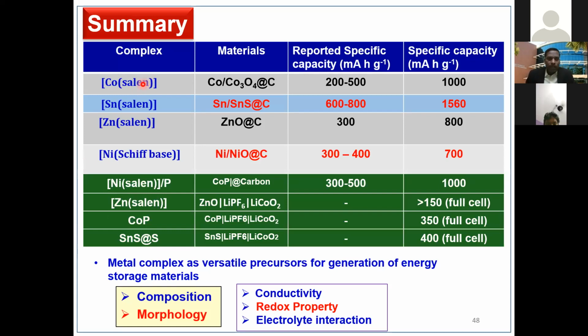So to summarize, we have explored a carbon-containing salen as a ligand to make metal complexes. And by decomposition of these metal complexes, we got these metal oxides embedded on the carbon matrix. And you can see that their capacities are much higher. Especially look at the full cell capacity. And in the case of tin and tin sulfide, 400 mAh is the full cell capacity.